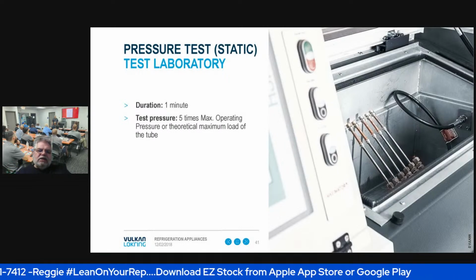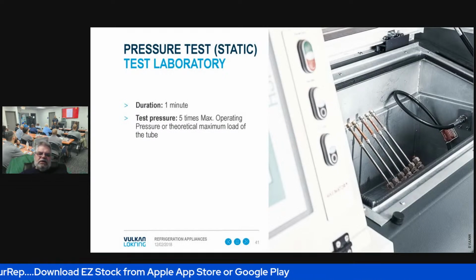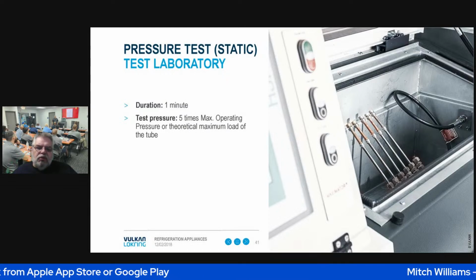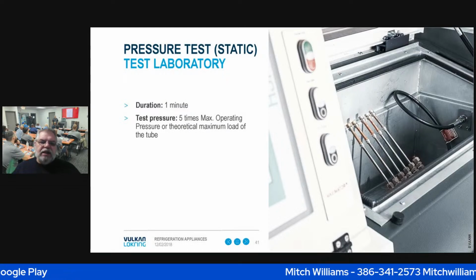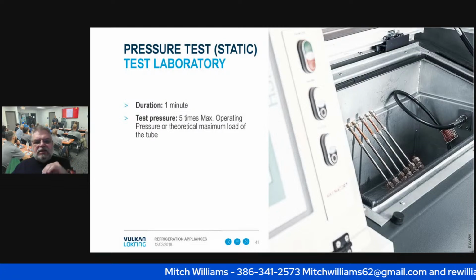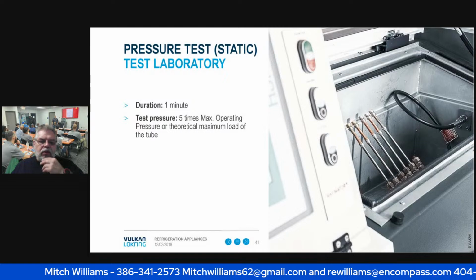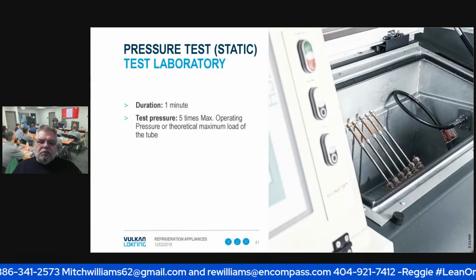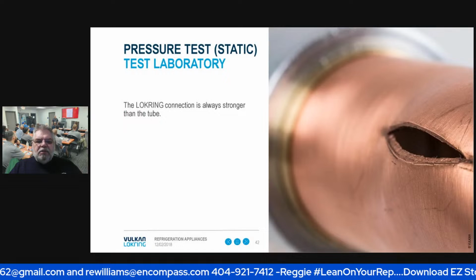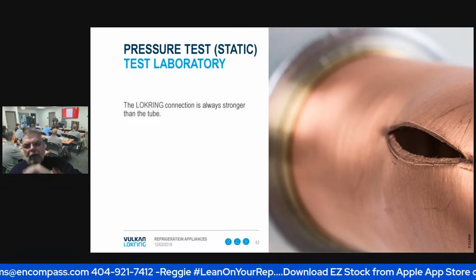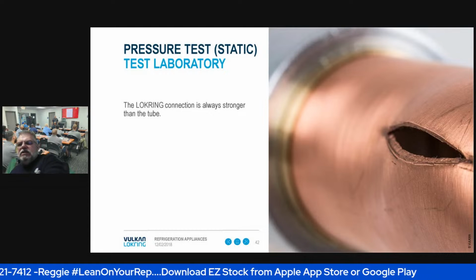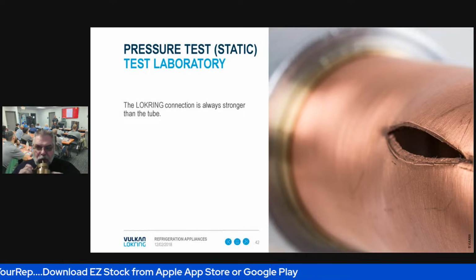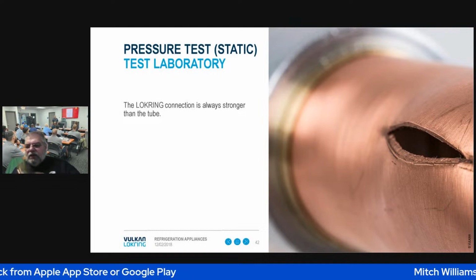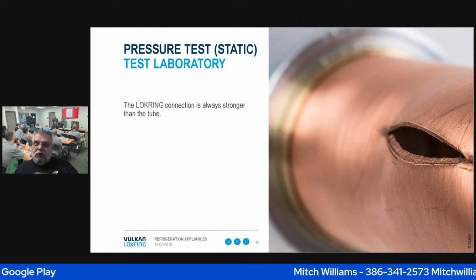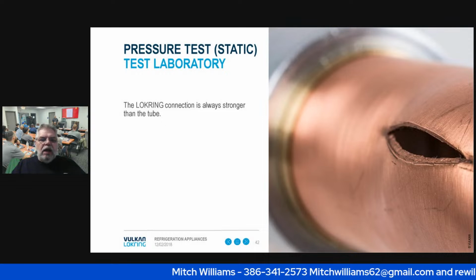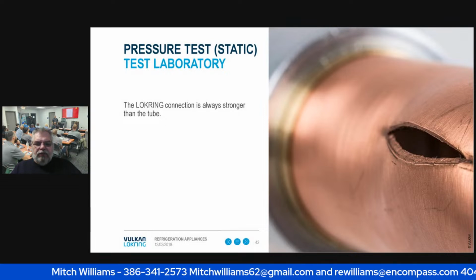The last thing that we do is our pressure test, and that's a static test. We do this for 1 minute. The pressure test is 5 times the maximum operating pressure or the theoretical maximum load of the tube. One of the things about the pressure test: whenever they blow, they find that it's the copper that blows. This is an actual picture of one of the tests that blew out. The LokRing connection is always stronger than the tube itself.